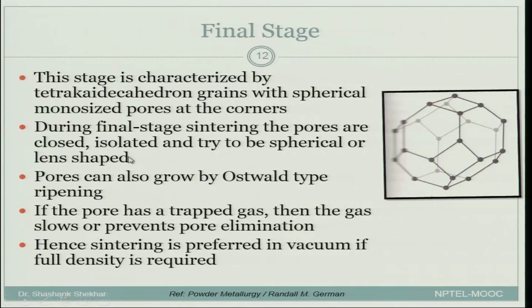During final stage sintering, the pores are closed, isolated, and try to be spherical, because the surface energy term will try to reduce, and that happens best when the pore is spherical in shape. Pores can also grow by Ostwald type ripening. Like the particles ripen by Ostwald ripening, similarly pores can also grow. If the pore has a trapped gas, now we are doing it in some atmosphere, so inside this there is still some of that gas remaining. So, that gas is now trapped inside.